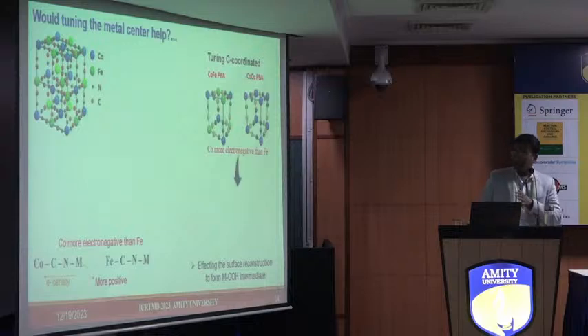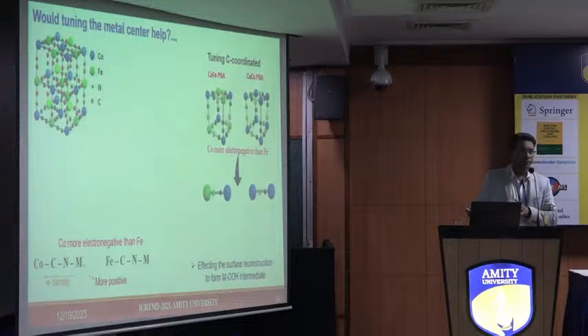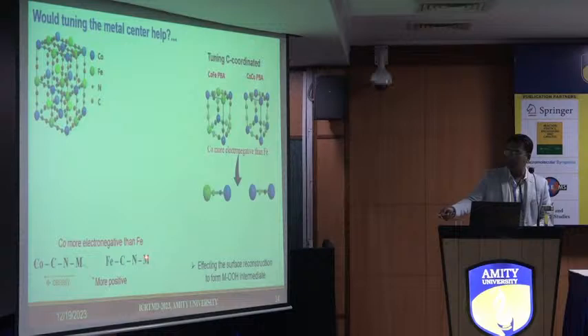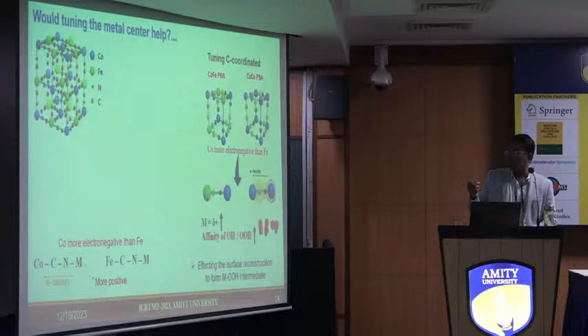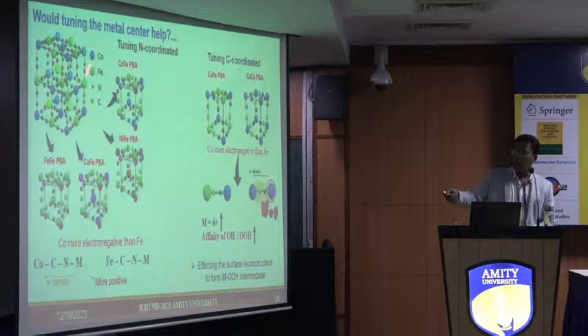So we played with simple inorganic chemistry, and what we did is we tuned the centers. You can see there are two different types of centers. This is the cobalt, for example, carbon, nitrogen, another metal, or the iron, carbon, nitrogen, another metal. You can change these metal centers, or you can fix this metal center and change cobalt to iron. This is what we have done. We call it the carbon coordinated one, and the other one the nitrogen coordinated one. For the nitrogen coordinated, we changed to cobalt, nickel, copper, and iron. And for this, we could change only the iron and the cobalt.